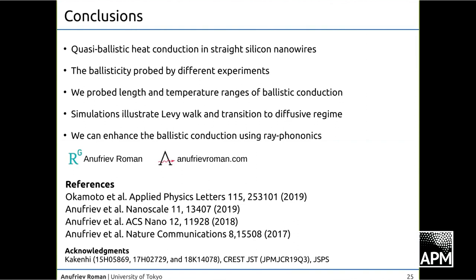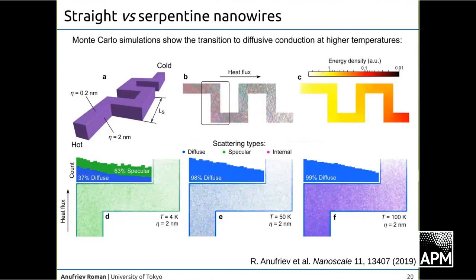And regarding the anharmonicity, indeed, phonon scatterings are much weaker at low temperature, as I tried to show in the simulation. Basically, at 4K, we have nearly no internal scattering events, which is kind of an anharmonic process, if we are talking about the same anharmonicity. So indeed, the role of anharmonicity is strong, and the role of quantum effect in the sense of wavelength dependence on temperature is very strong, is the main mechanism. Does it address your question?